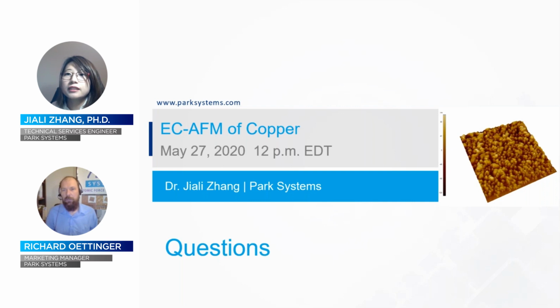So we show that this one was scanned after the reactions, but in this experiment, scanning was done during the reactions. That's why you can see the copper domains at the beginning, then diminishing, and completely dissolved, and the bottom gold was exposed. Of course, you can apply negative potentials and see the backward reactions happen.